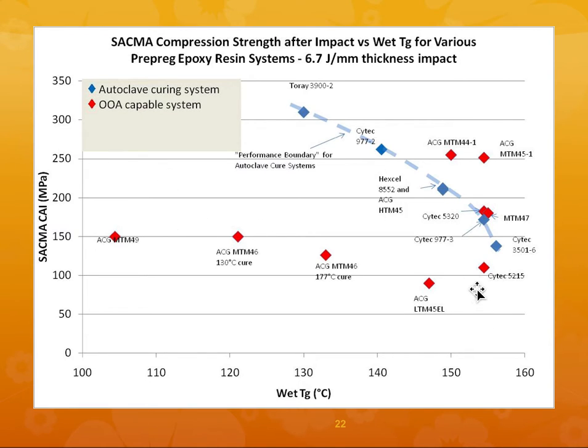So you can see that this is the standard material properties, and if you increase the temperature to which these are exposed, the standard material has a reduction. It's compression strength after impact versus wet Tg for various pre-preg epoxy resin systems. So this is the autoclave curing system, and this is the out of autoclave capable system. So what you can see is that the out of autoclave system is even better than the autoclave curing system, even after exposing to wet conditions and higher temperatures.